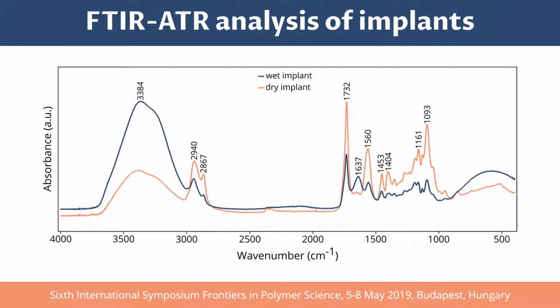FTIR-ATR spectra of implants show similar features. Bands characteristic for polyacrylic acid hydrogel are present in the spectrum of wet implant, while the bands corresponding to the hydrophobic polymer matrix dominate in the spectrum of the dry implant. Absence of band shifts also indicates physical blending, as in the case of membranes.